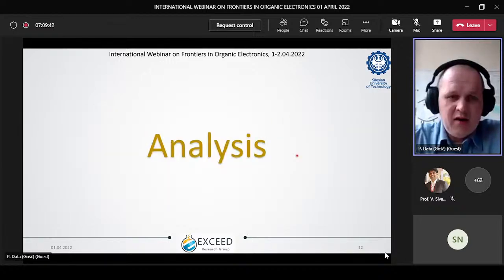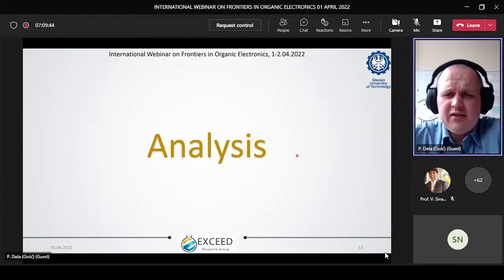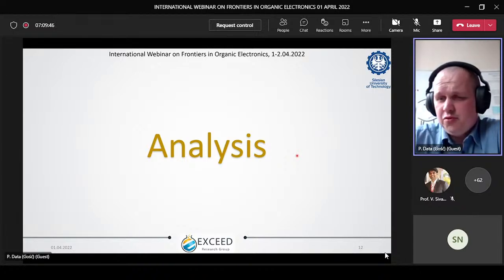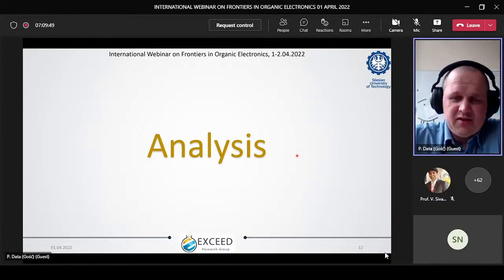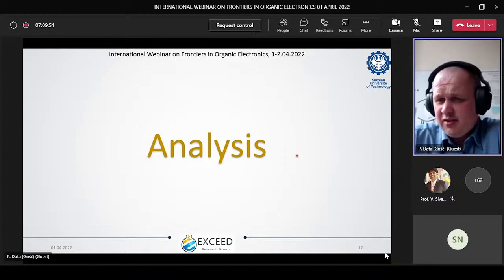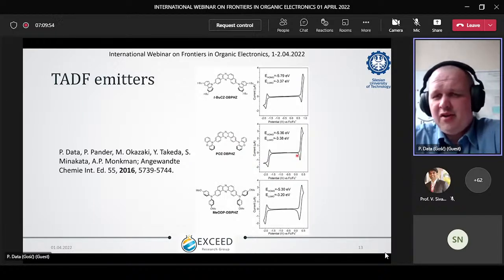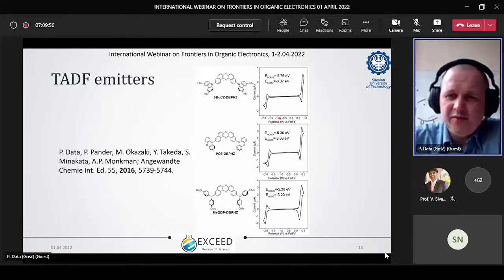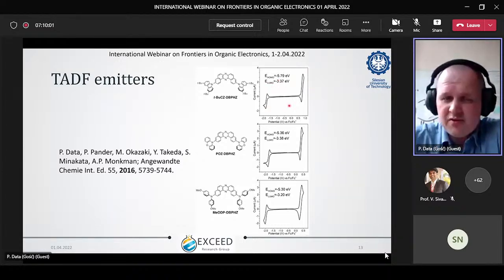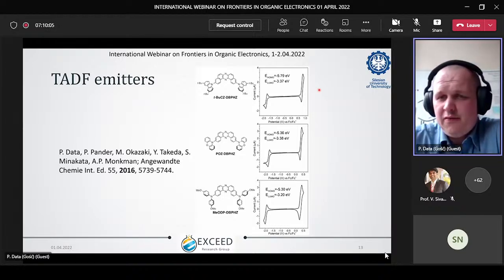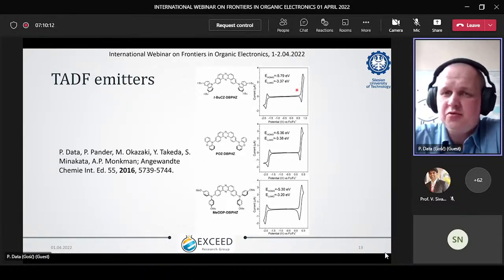I forgot about that. So, analysis. How to analyze your organic compound to use as OLED emitters, TADF emitters. First, in our case, we are doing the electrochemical analysis, which is one of the simplest. You have cyclic voltammetry. Why? Because of two reasons. Firstly, to check if our compound is ambipolar. So if we can inject both electrons and holes, because that's important for the devices.